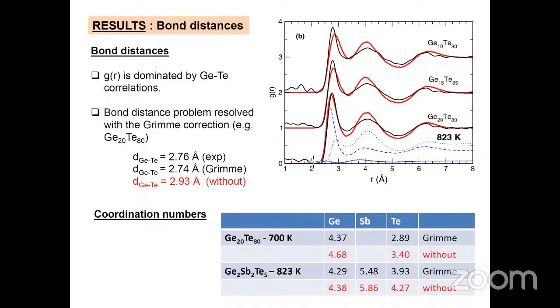So in fact, if we look into details, into partials, let us take the Ge20Te80 in the liquid. We see that this structure is dominated by a main peak which arises from GeTe correlations. There is a minor contribution which arises from TeTe correlations, and then a very small contribution that you see as the blue solid line here, which arises from GeGe correlations. So we realize that the bond distance problem in those tellurides is resolved with the Grimme correction. Here I provide you numbers for this main peak of the GeTe correlation. We see that with the Grimme correction, the distance is very close to the experimental one, whereas without it, it is substantially overestimated.